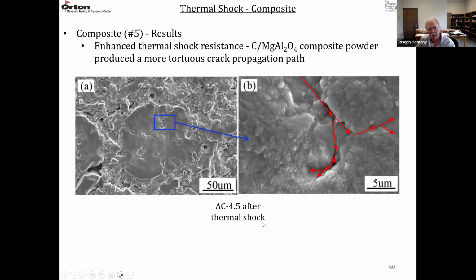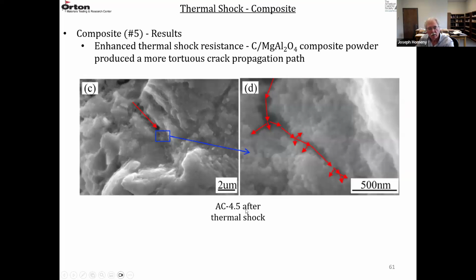So this is AC 4.5 again after thermal shocking. And this is one of those aggregates where you have the graphene carbon layers in the spinel. And then they're highlighting this area here where the crack is branching, it's branching again and again. So it's a more tortuous cracking type path. This is just another example of AC 4.5 after thermal shocking. And they're showing this area enhanced over here. The crack is branching, and then it's continuing to branch all along this path. So these composite powders are creating more tortuous crack paths.